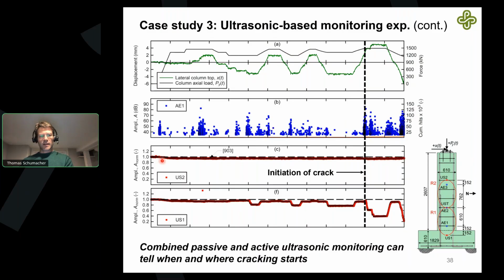And then you can see here the upper and the lower ultrasonic transducers embedded in the concrete. The top one, throughout the loading process, had a constant amplitude for the signals, and the bottom one started to actually pick up some changes when we varied the lateral displacement. So this path down here started to get cracked, and we could actually see that. And so actively, you can see when stuff is happening, when you have cracking, in real time. With the active ultrasound, you can detect teeny little changes over time.